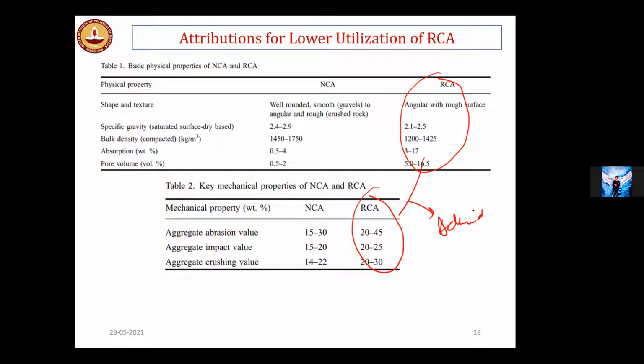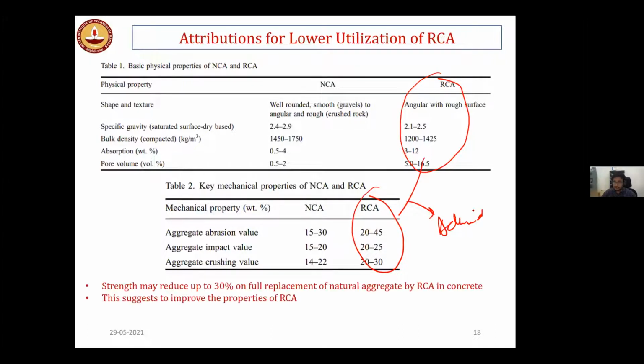And then if you are using this recycled aggregate in the concrete, there could be 30% strength reduction. So let's say for the structural application, if you want to use M40 grade concrete, and if you are using recycled aggregate, it could reduce the strength by around 30%, right? So it's a significant one, and you don't want to take the risk. That's why the code says there is no need to replace the aggregates fully, but you can go for a proportion of, let's say, 25% or 20%, and it could save a lot of natural aggregates.